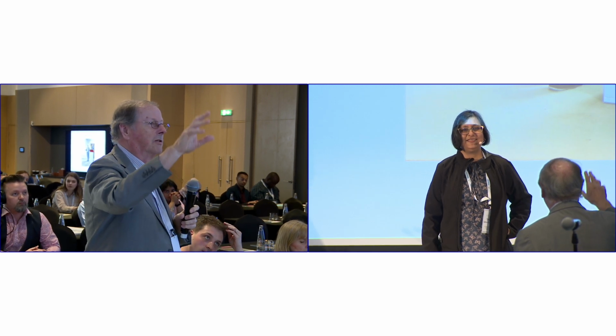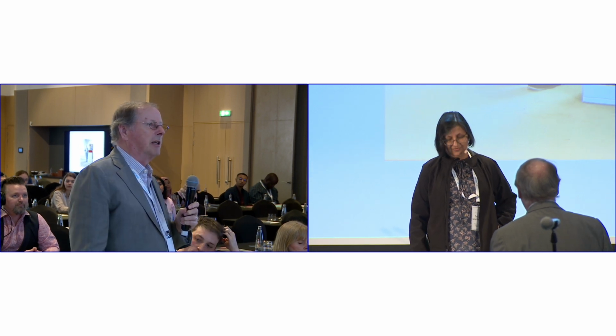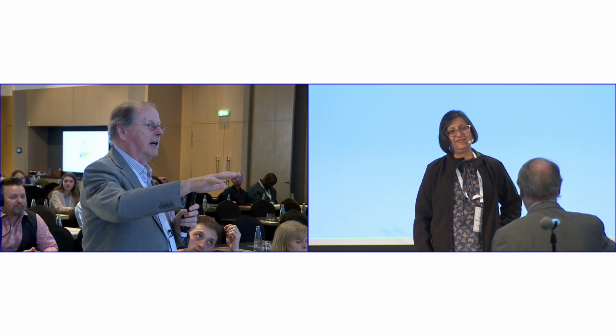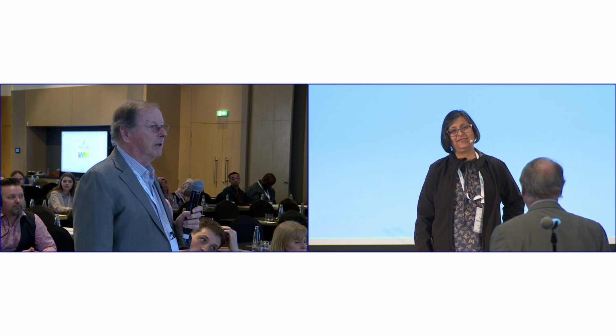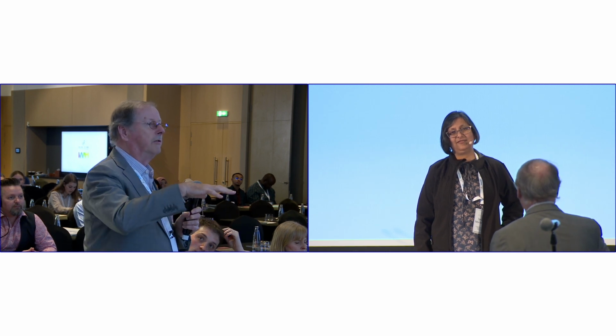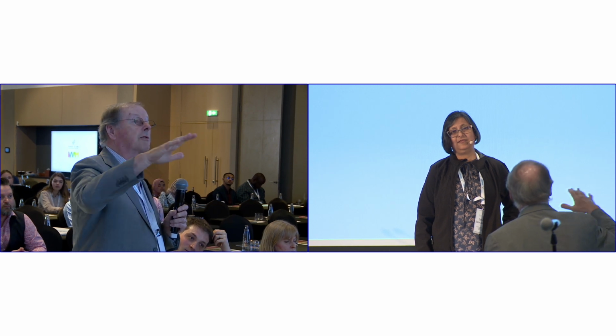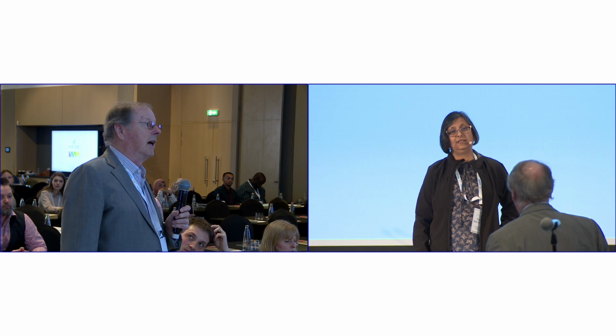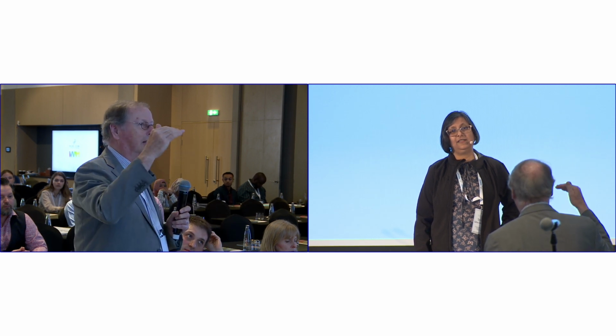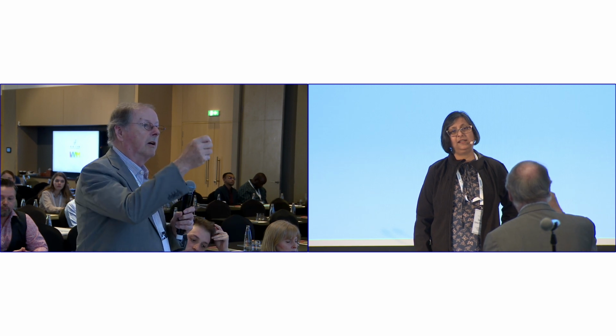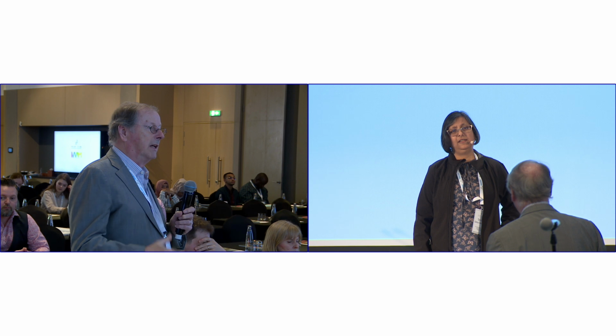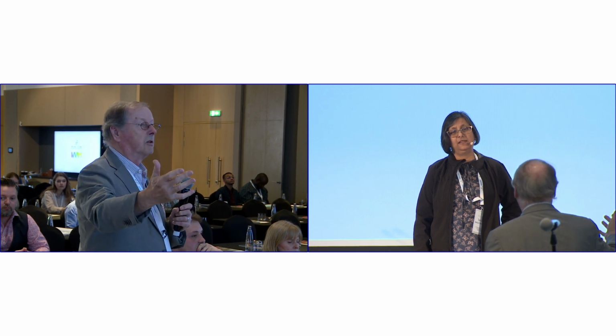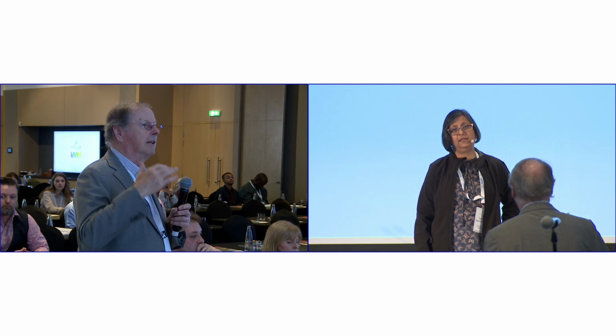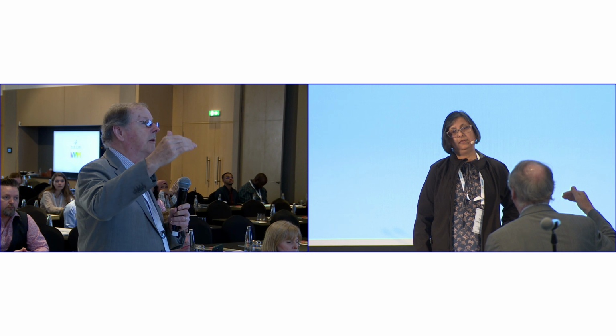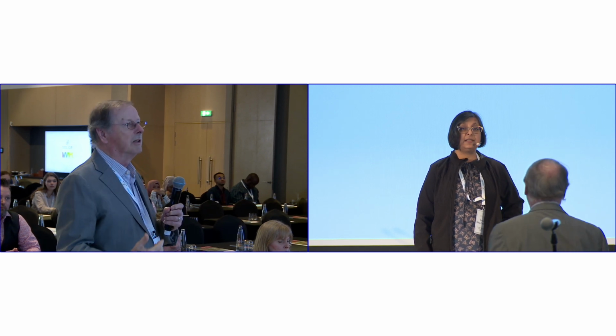It's a comment, really, because you said you didn't calculate the 2+2+ magnetic ground states because you thought they might be disordered. I think you might get a surprise and find that they order. We found in work we've been doing recently on formates that we can get ordering of 3+3+ formates. I wouldn't have believed it had we not actually done it and found it. So one thing you could do, though it's a bit more difficult, is to do the 2+2+ ones ordered and then estimate the difference in energy as to whether they're ordered or not. Obviously, that is indeed possible.